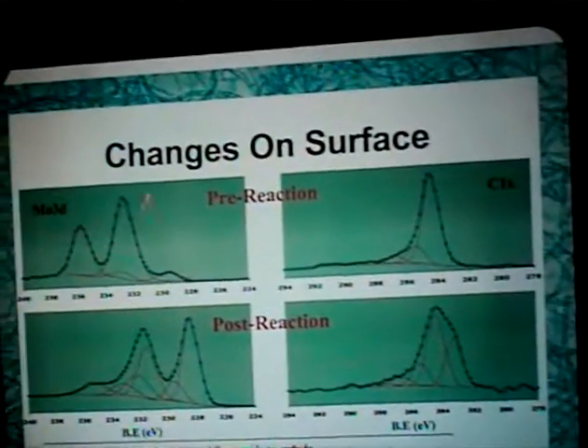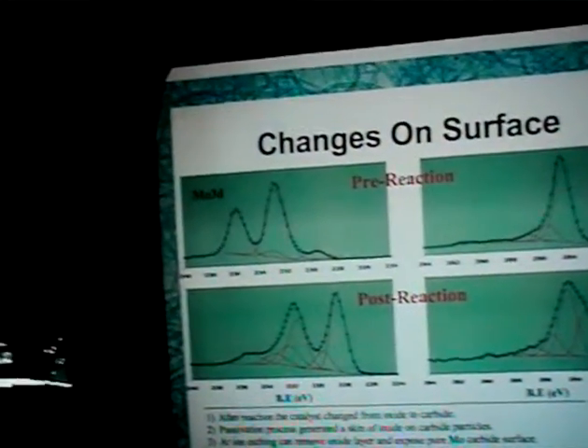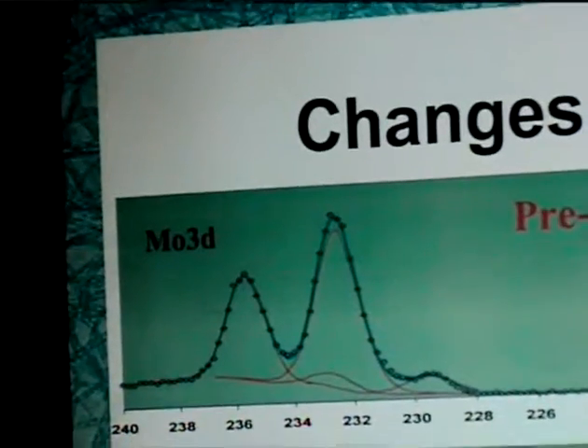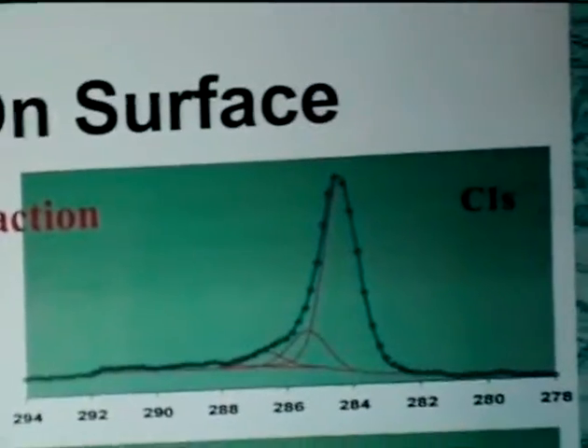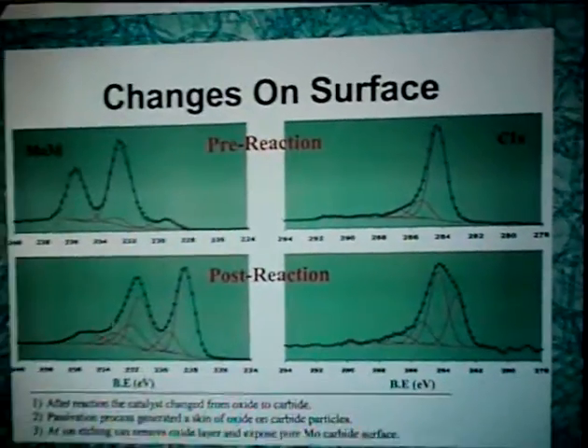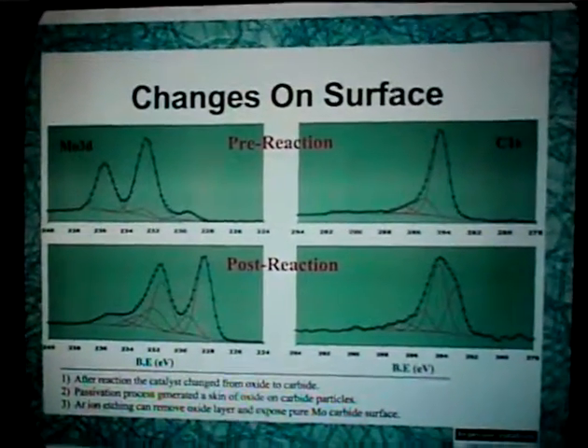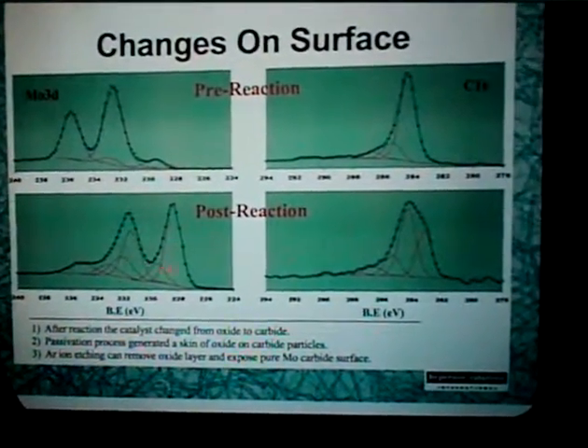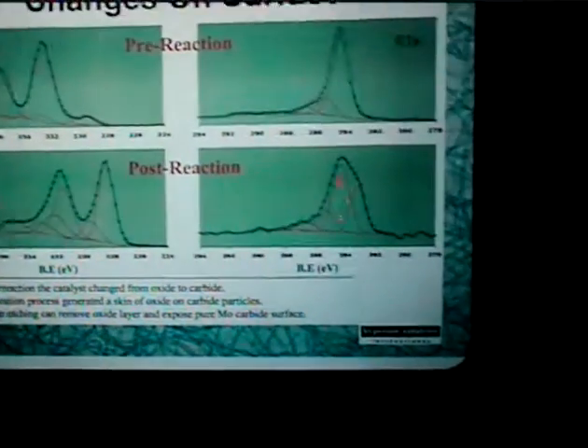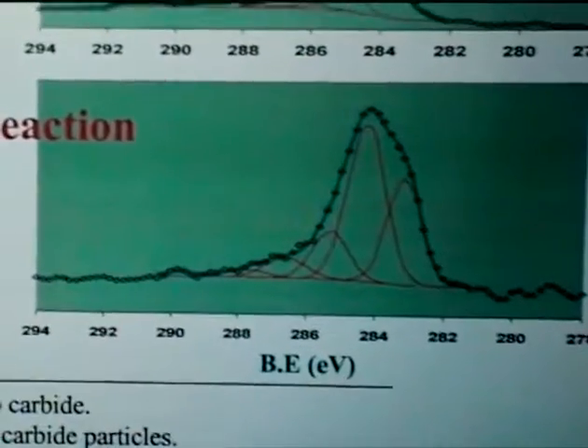You'd get, I would guess, a much better, much smaller particle size. So here's the XPS characterization before and after reaction. This is the typical peaks of molybdenum oxide before reaction and the carbon impurity. And after reaction, there is also passivation, so this is not in situ, so the sample is prepared and we have to passivate. So you get now a mixture of, you see molybdenum oxide because of the passivation layer, and the molybdenum carbide appears here, and also the characteristic peak of carbon and carbide.